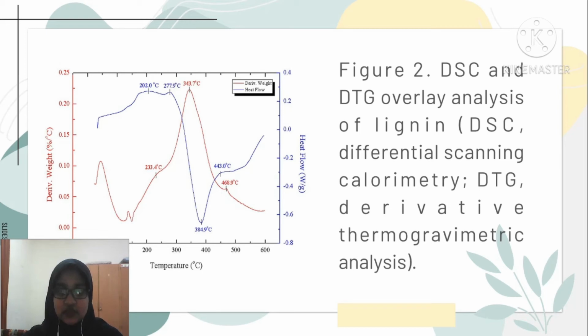Lastly, to conclude for the lignin, there is an endothermic peak observed at 202 Celsius with a loss of mass peak at 232 Celsius, while a smaller endothermic peak was observed at 277 Celsius, followed by a strong exothermic peak. Additionally, strong loss of mass occurs at 343 Celsius, while exothermic processes peak later when the rate of loss of mass decreases.